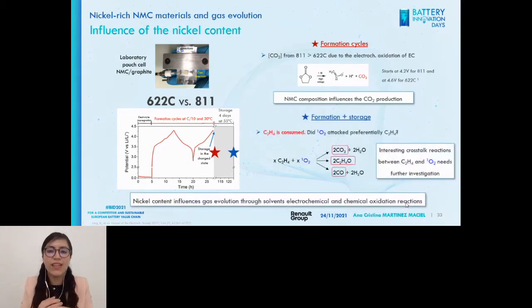Then, after the formation cycling steps and the storage, we saw that one of the gases, the formation gases that we thought had nothing to do with the positive electrode, was actually being consumed. We repeated this to make sure this was not something that happened in just one batch, so we did this on several batches, and we were able to see that the ethylene gas was in fact being consumed.